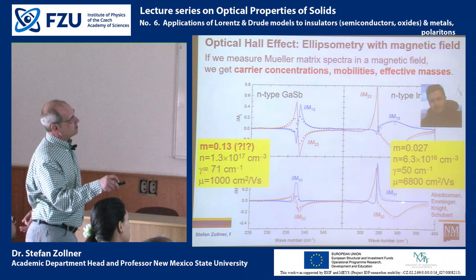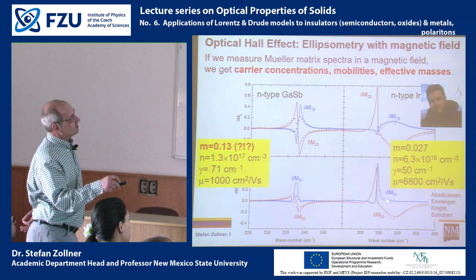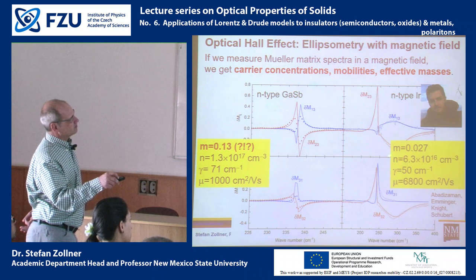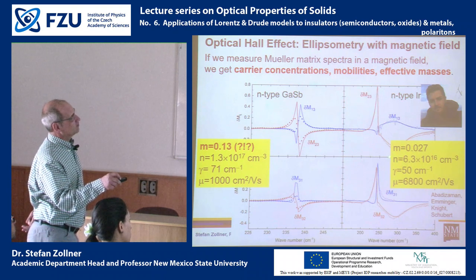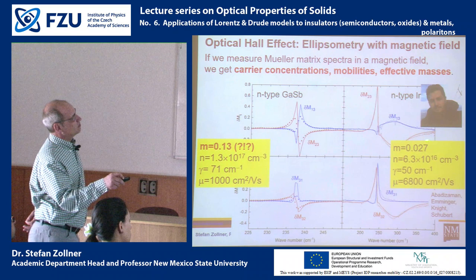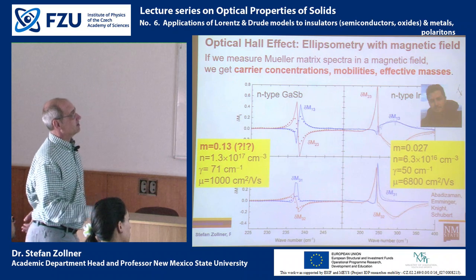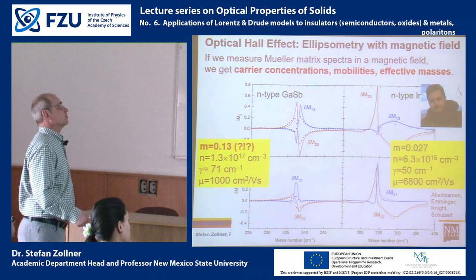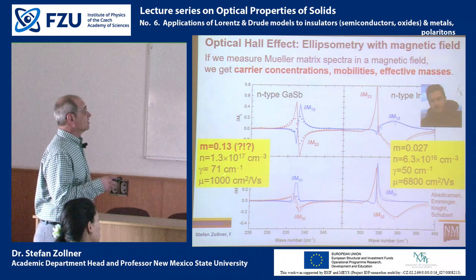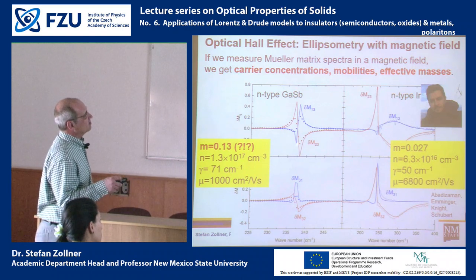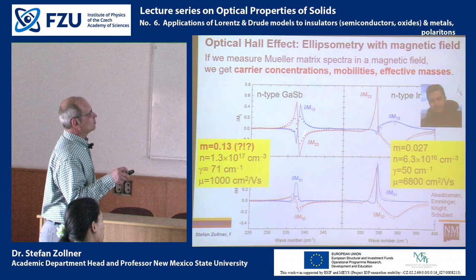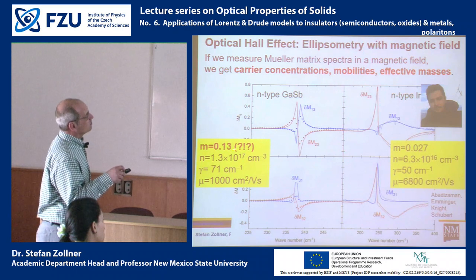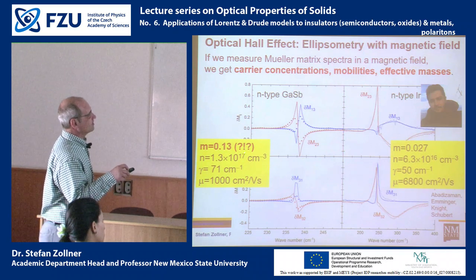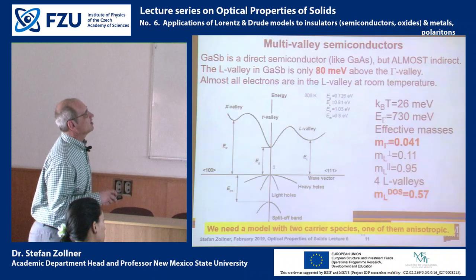So we're getting these peaks here, and if we fit that with a model, and if the magnitude of the magnetic field is known, then we are able to determine the effective mass because now we have a magnetic field. For gallium antimonide, the fit is not so good, and we're still working on that, but most of all, the effective mass is completely wrong. And why is that?